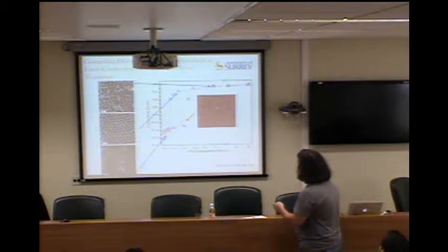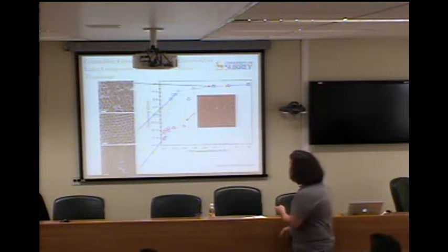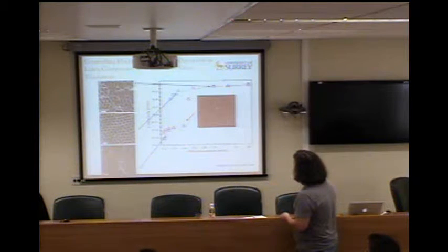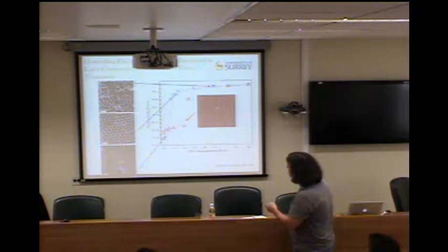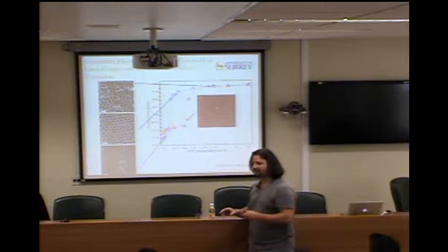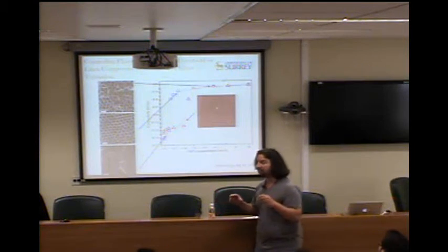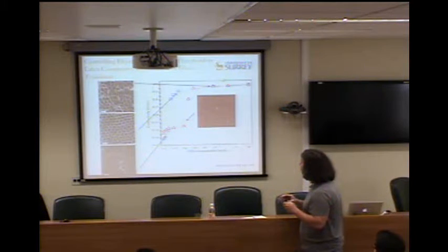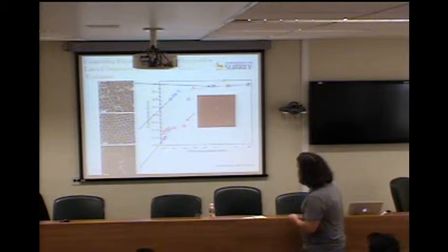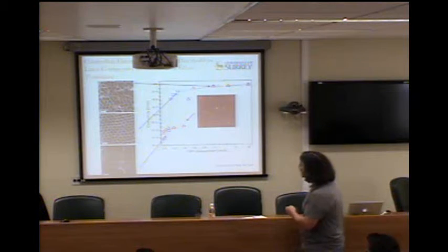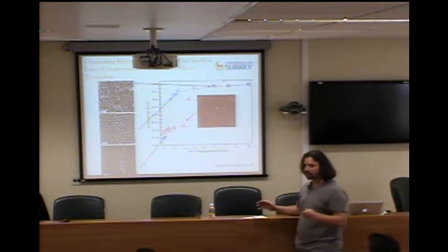So if we look at the conductivity versus carbon nanotube concentration, okay, so for the isotropic system where the carbon nanotubes can kind of go everywhere, we see this behavior where this percolation threshold happens at around 0.4%. In the segregated network, where we're now forcing the nanotubes to go to smaller volume, or there's lower fractional volume for them to exist in, we now have this percolation threshold down at 0.1% or so, which of course is 25% of the original one. So it works.